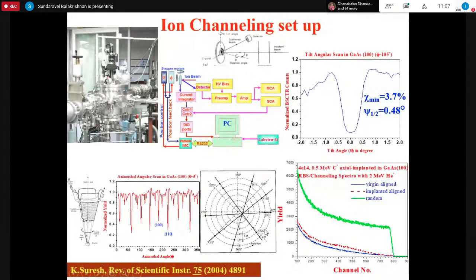So we mark these 8 prominent dips, and if you want more precise alignment, one can do it instead of 5 degrees, one can tilt by 6 degrees and take one more spectra like this. Then those points also can be plotted, and then we join those points in the upper quadrant with respect to the lower quadrant, and all the lines in this polar plot will be meeting at one point. At that point, find out the value of theta and the value of phi, and we set that value of theta and phi, and at that position the crystal will be aligned.